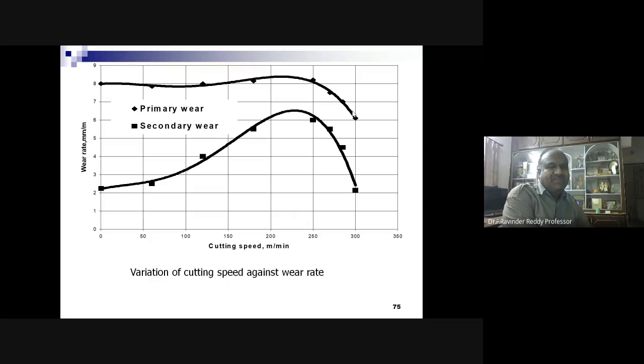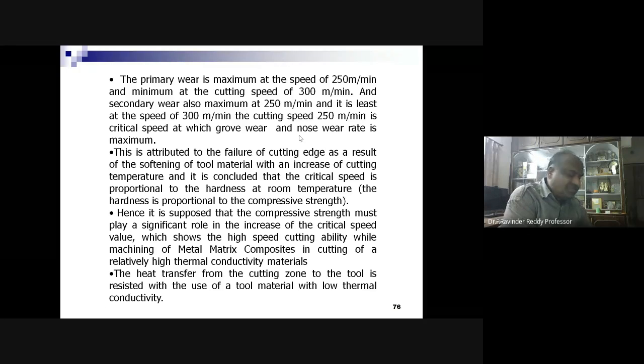If you see the primary and secondary wear against the cutting speeds in meters per minute, you can see the primary wear is high compared to secondary wear. Both of them are increasing up to 250 meters per minute, and afterwards decreasing. From those graphs, we can observe that the primary wear is maximum at the speed of 250 meters per minute, and minimum at the cutting speed of 300 meters per minute. The secondary wear is also maximum at 250 meters per minute, and least at 300 meters per minute.